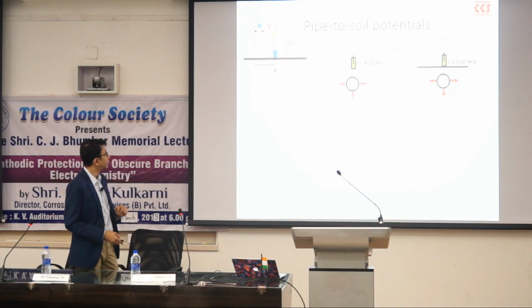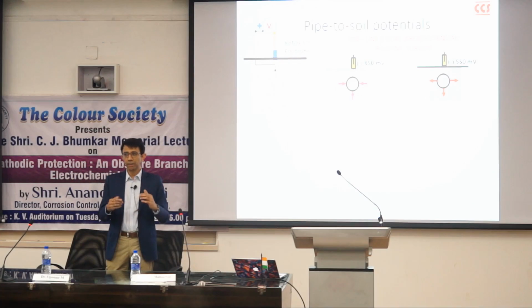These are pipe to soil potentials, and I want to show you how you actually take this measurement. This is a pipeline. This is the reference electrode. You connect the reference electrode, and as we saw earlier, it's a copper sulfate. You connect it to a high impedance voltmeter, and these are direct current measurements, DC measurements. So the positive terminal is connected to the pipe, the negative to the voltmeter, so that you can get the pipe to soil potential with reference to the electrode.